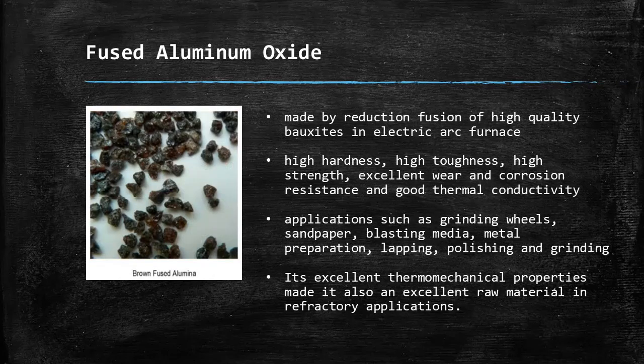Brown fused alumina, BFA, is made by reduction fusion of high-quality bauxites in electric arc furnace. Typical composition is 96.12% Al2O3, 2.70% TiO2, 0.67% CaO, 0.11% Fe2O3 and other oxides 0.40%, trade name, Duralum. Its notable properties are high hardness, high toughness, high strength, excellent wear and corrosion resistance and good thermal conductivity. With its indispensable mechanical properties, it is commonly used in applications such as grinding wheels, sandpaper, blasting media, metal preparation, lapping, polishing and grinding. Its excellent thermomechanical properties made it also an excellent raw material in refractory applications.